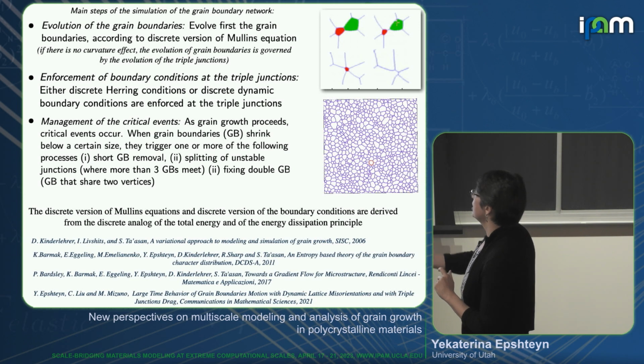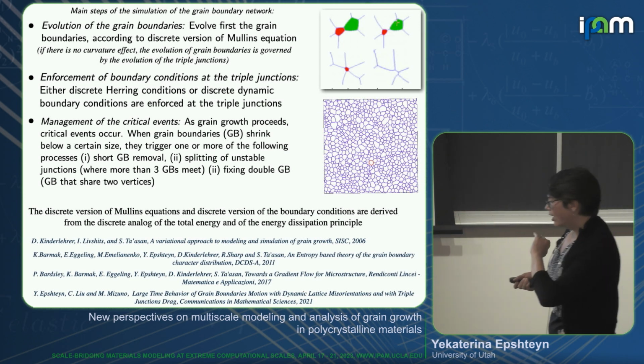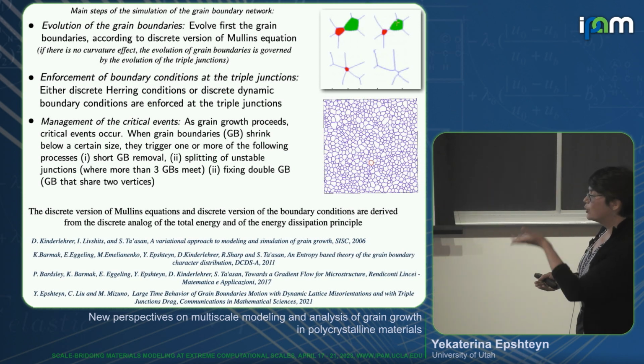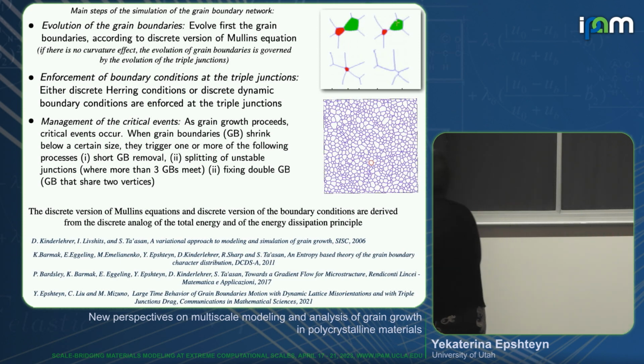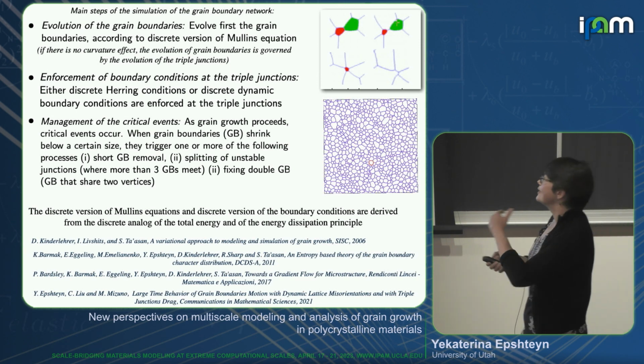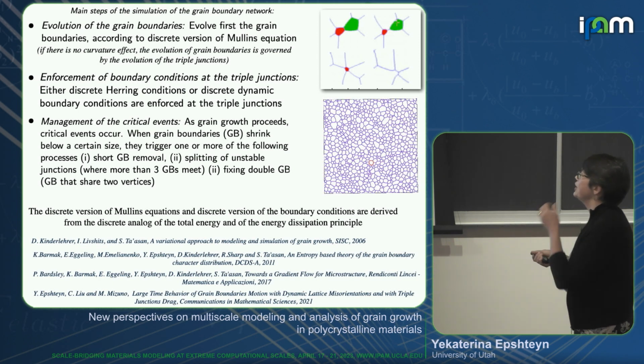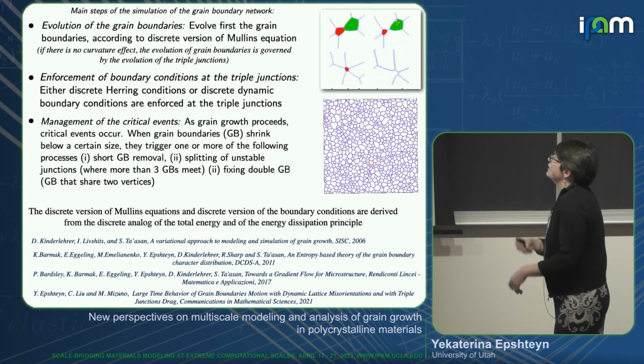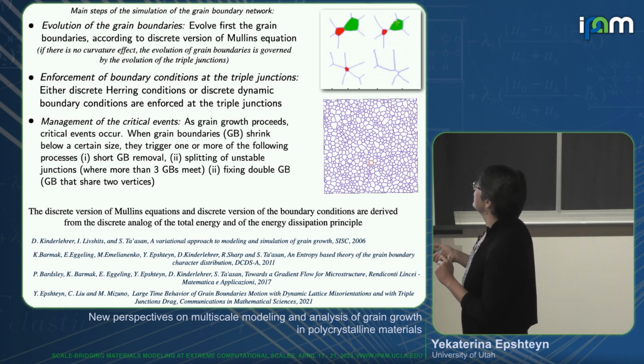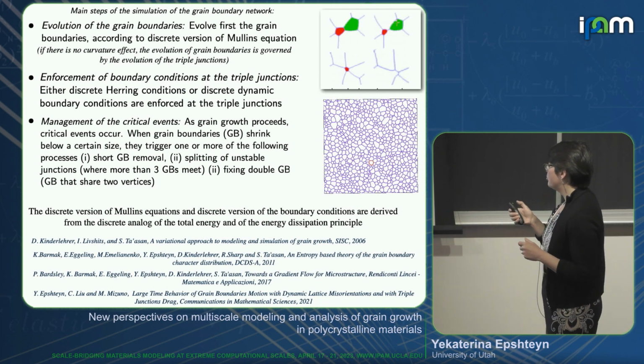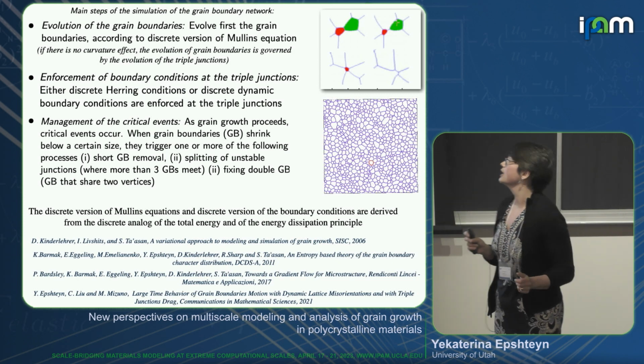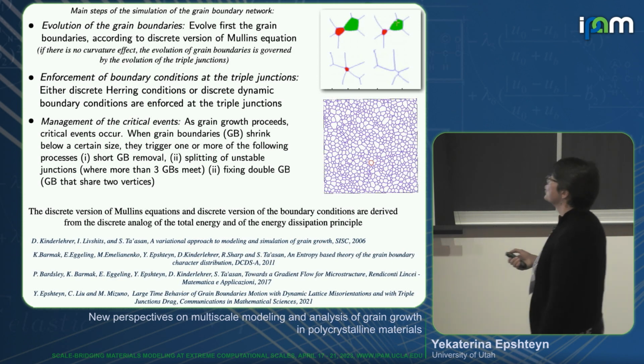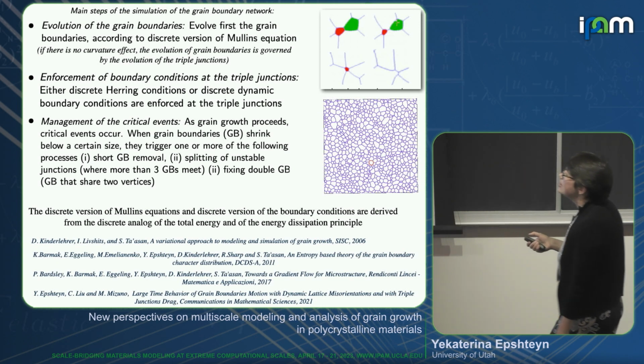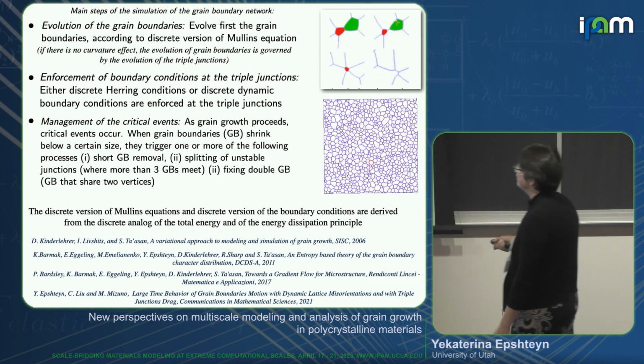So I will only mention 3 big building blocks of simulations. The way the numerical scheme is derived, we compute a discrete total grain boundary energy. We enforce at a discrete level the dissipation of total discrete grain boundary energy, and as a result of that, we derive a discrete version of Mullins' equations if we take into account curvature effect. We take into account dynamics of grain boundaries. If we relax dynamics of grain boundaries, then it's basically a vertex type model, and the dynamics of grain boundaries is really defined by what happens at triple junctions. We enforce boundary conditions at triple junctions, either discrete force balance conditions or discrete dynamic boundary conditions in case of finite mobility of triple junctions.